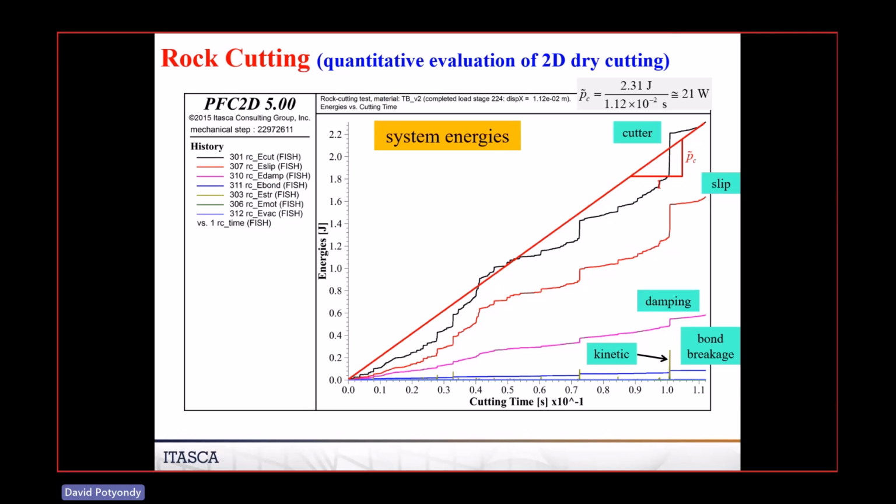We have a damping mechanism that we use. It's very good at removing all that vibrational energy in the system. And so that's consuming energy. But then most of the energy is actually going on frictional slip between either the two surfaces of the particles or between the particle and wall. Because remember, the particles are getting slid across the wall.